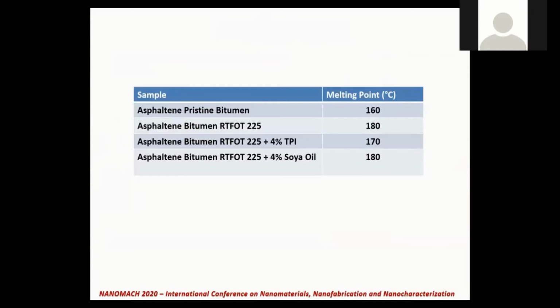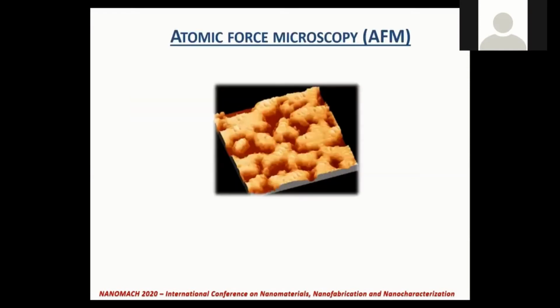In this case, it is possible to observe a significant difference between the asphaltenes derived from the samples of aged bitumen modified with soy oil and TPI. Thus, we can say that the regenerating additive TPI has chemically interacted with the asphaltenic part of the bitumen, restoring it almost totally to its initial state, while soy oil, having simply improved the flow of the aged bitumen and therefore not having chemically interacted with the bitumen, shows a behavior very similar to aged bitumen.